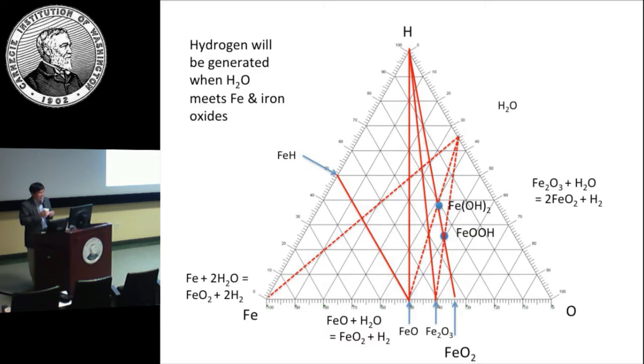Zach, do the densities make sense, like that this would be a pressure-driven decomposition of FeOH? Is FeO2 becoming very dense with pressure? You actually measured densities of some of these phases. So do the thermodynamics make sense that it's pressure-driven? The thermodynamics makes sense, yes. Is FeO2 at like 30 GPa less dense? So we did a reversal reaction, and the reversal reaction has to be done at high temperature and then to low temperature, ambient temperature. By just decompressing, it just decomposes. It somehow collapsed. We don't know whether it became amorphous or decomposed.